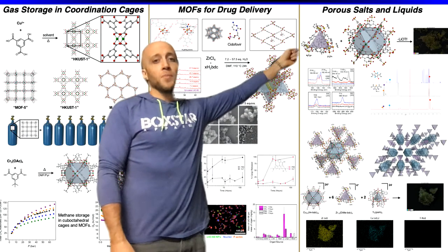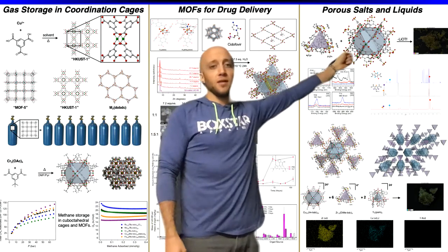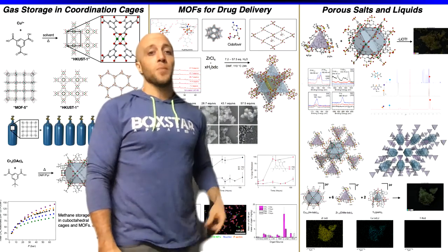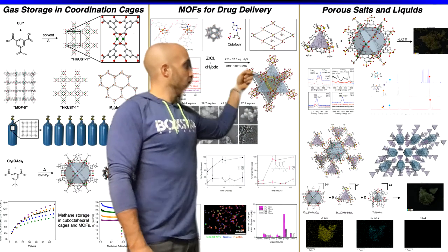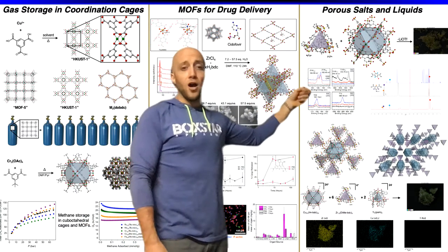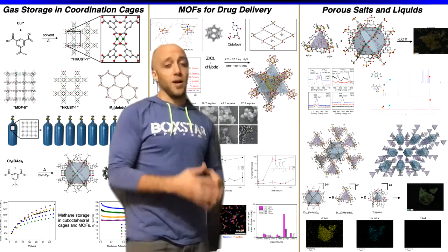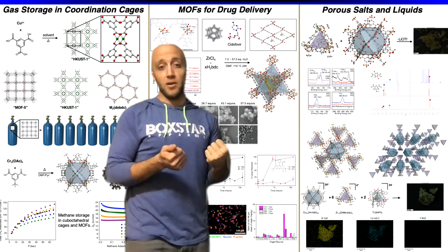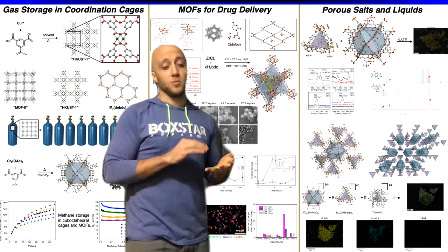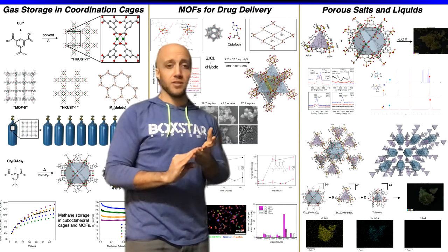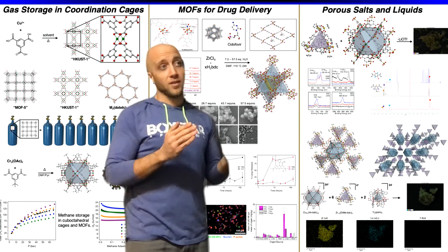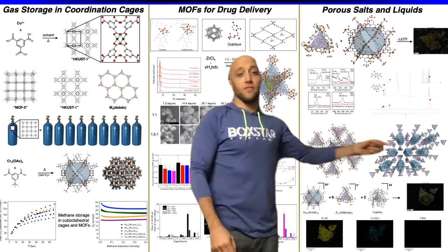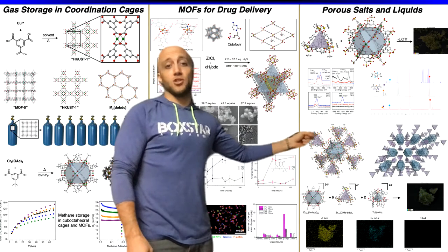So here's an example. Zirconium cationic cage plus a copper anionic cage gives us an amorphous, a non-crystalline sample. Spectroscopically, we can see that in XPS, IR, NMR, the product phase that we couldn't characterize initially is made up of these two different cage parent types. So my students do a lot of spectroscopic characterization, physical characterization, and importantly, crystallographic characterization.